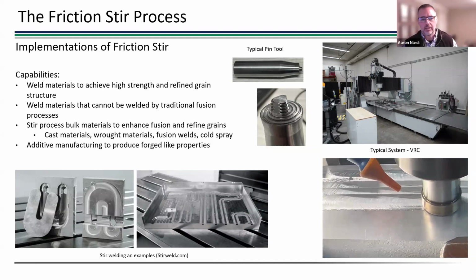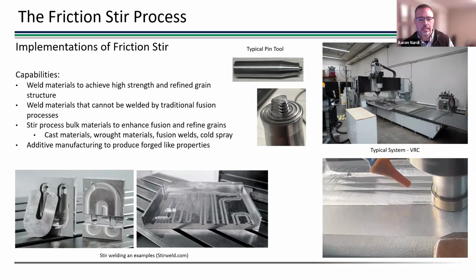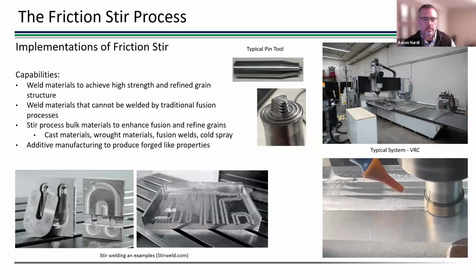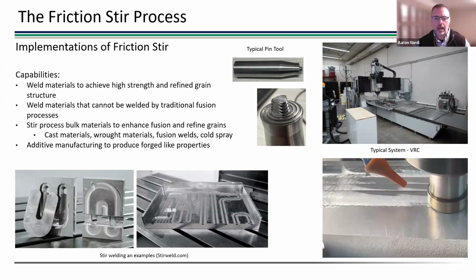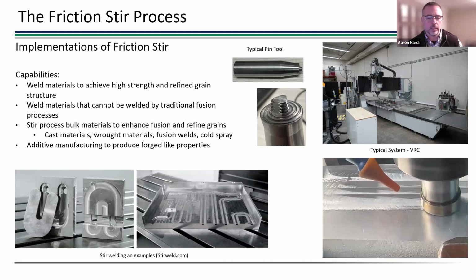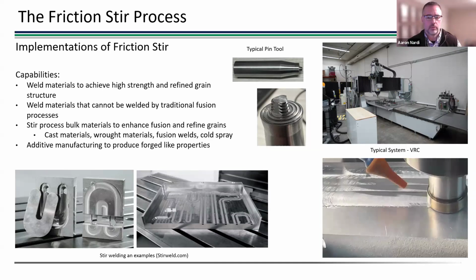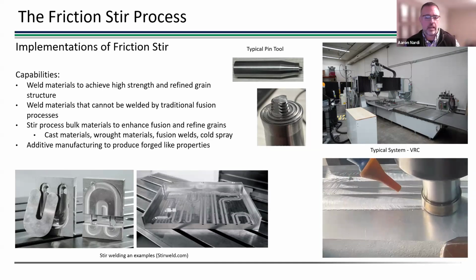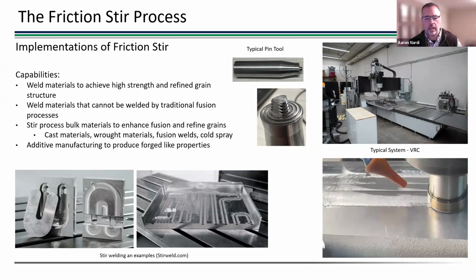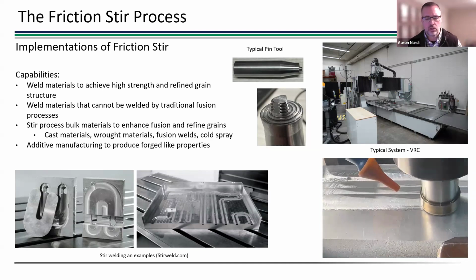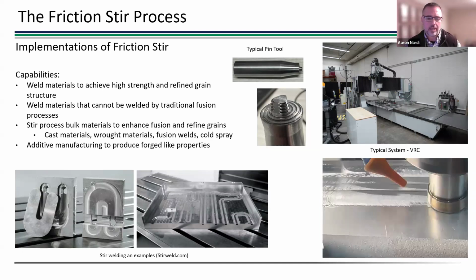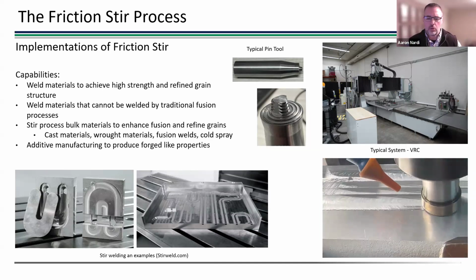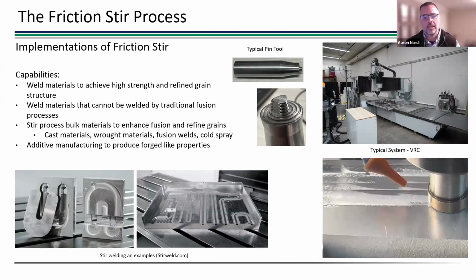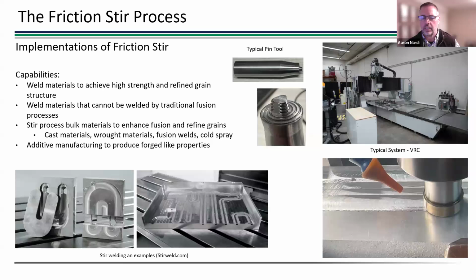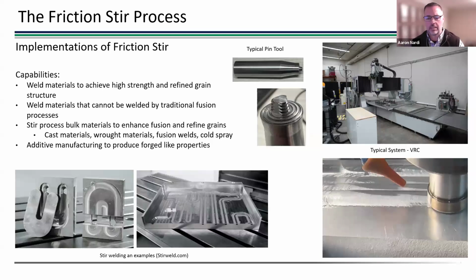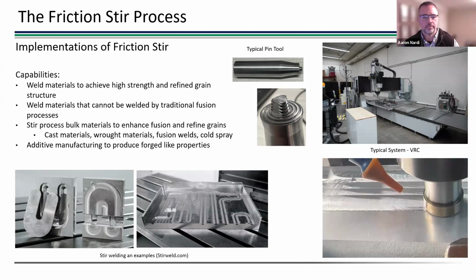Now, what's interesting is you can friction stir process a wide variety of materials too. This video is friction stir processing a plate of aluminum. This was cold sprayed aluminum. We've done a couple of different examples to date where we started with a higher spray process condition, and then did another one with a low spray process condition. And even in the low spray process condition with a lot of porosity, you can consolidate that material and get really, really good mechanical properties. So that's what you're seeing here.